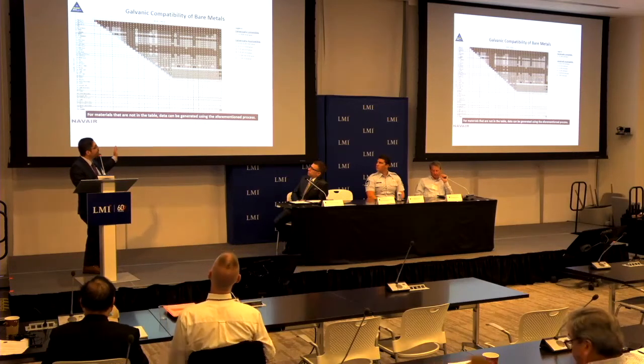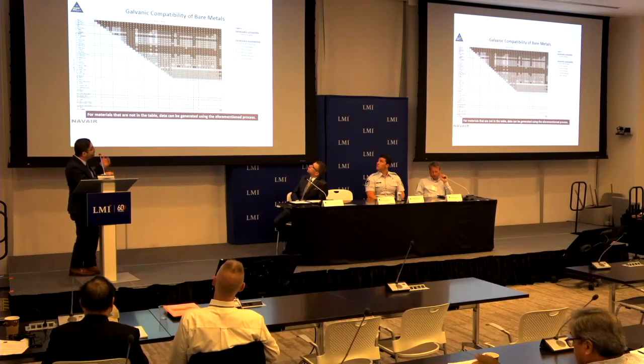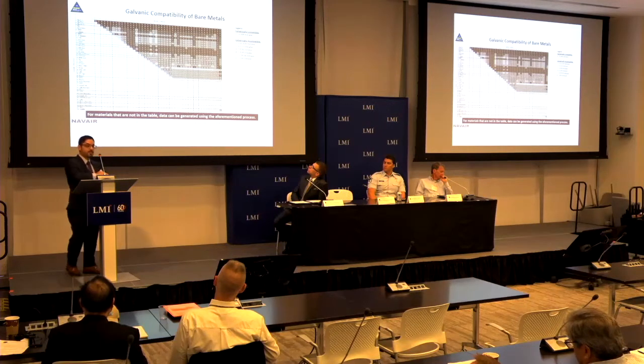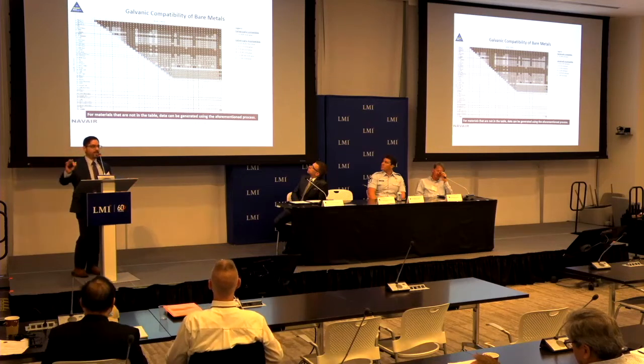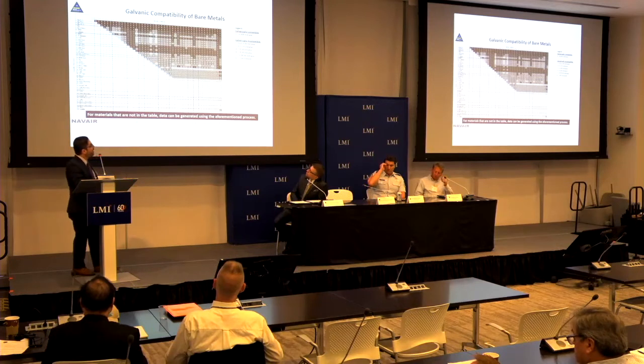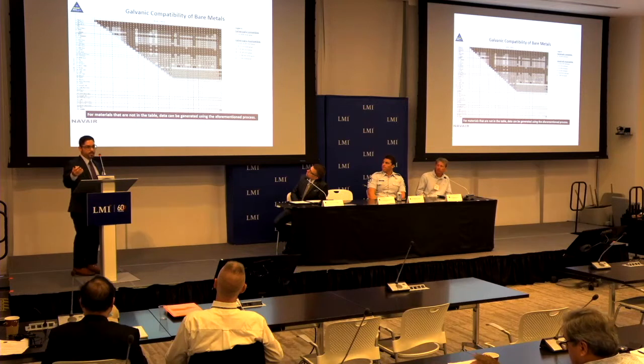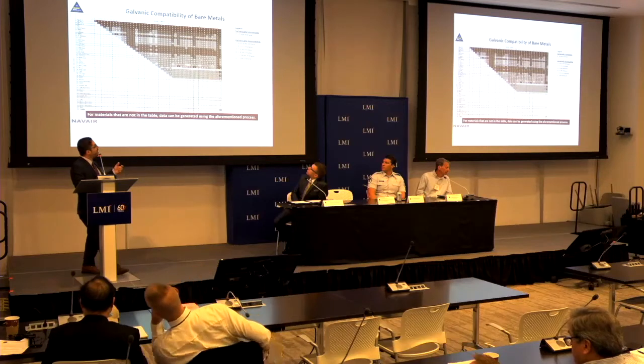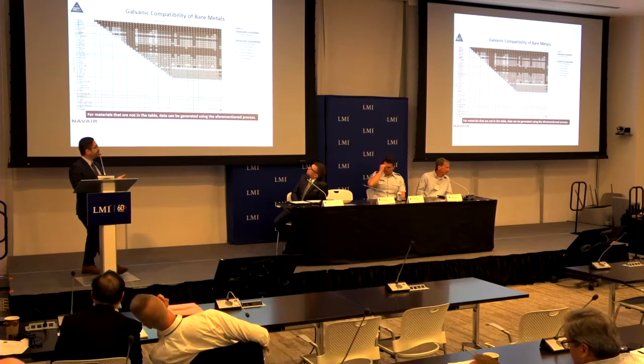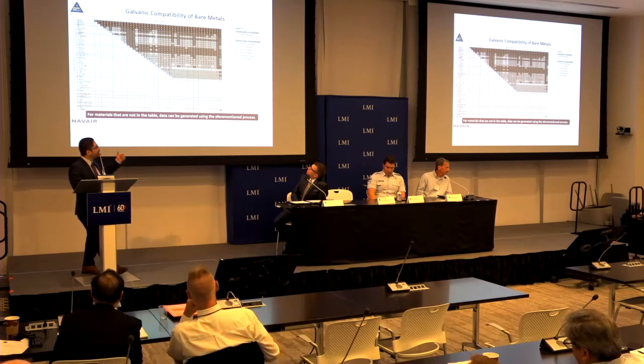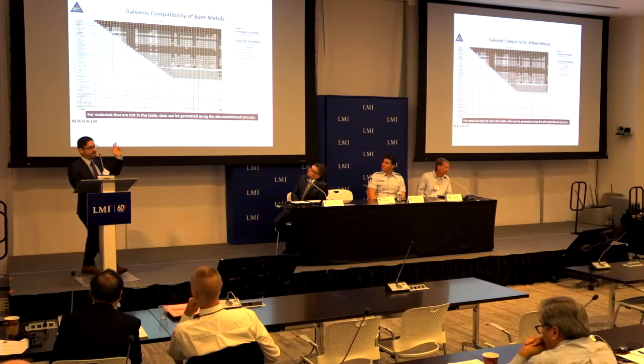Here, we're saying it is, but also there are levels of incompatibility, right? If it's rated as zero, mostly down here, those two couples are compatible, meaning that you don't have to do anything extra to protect them. Anything above a zero is incompatible. So for acquisition, it means you cannot put them together without protection. That's what it means for acquisition, right? But the added benefit for the subject matter experts who are working on this is that these levels of incompatibility give the SMEs the ability to provide risk assessments to the programs, right? So if it's a one, yes, it's incompatible, but that is not as bad as a six, right? So if you are at a six, you may want to throw the kitchen sink at that couple to protect it.